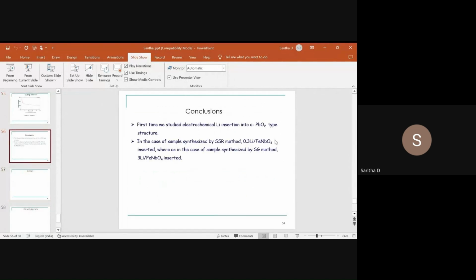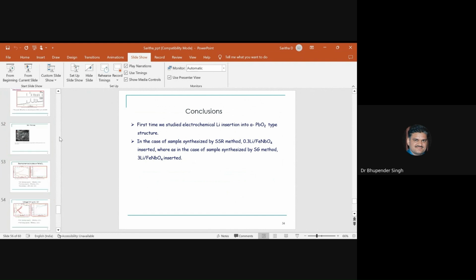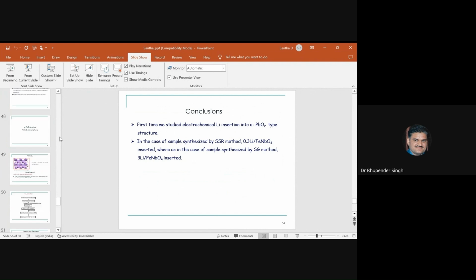What we discussed here was ReO3 structures, polyanionic compounds, and PbO2 type structures. In a few cases, they didn't work at the micro level, whereas when we moved from micro to nano level, there was a tremendous increase in lithium insertion, which finally leads to good capacity, and the cycle rate has also improved a lot compared to the micro. Thank you all.